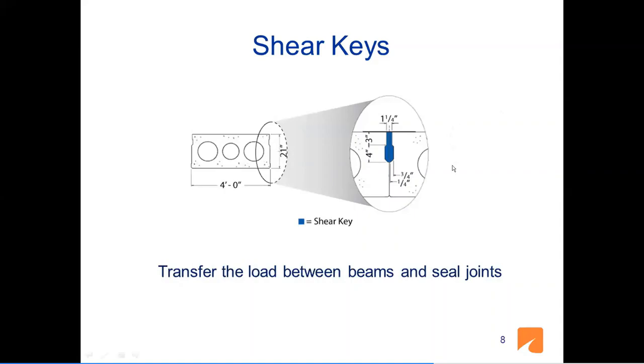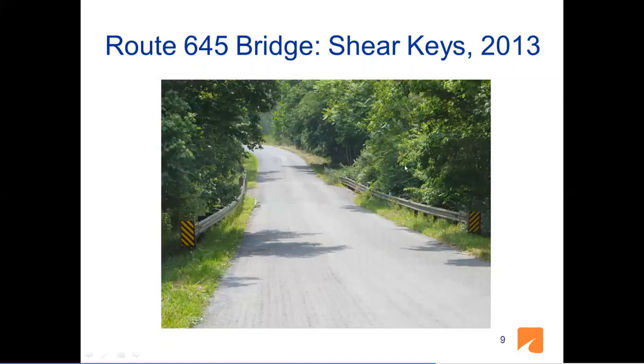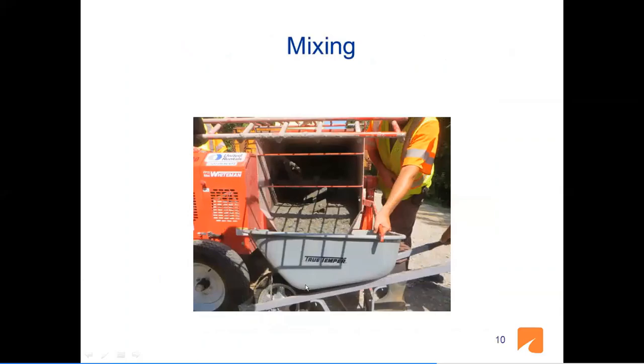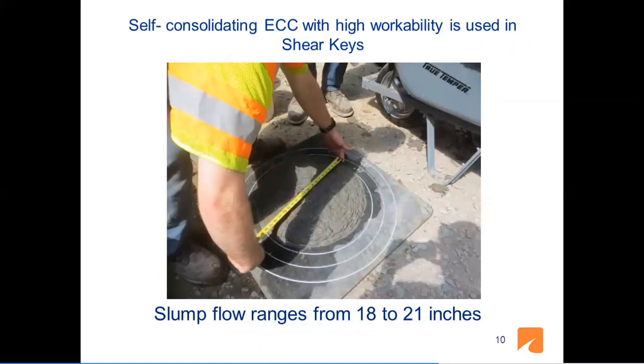So what we suggested is to use the fiber reinforced concrete, the ECC. So I'll tell you a little bit about that here. The shear keys basically transfer the load between beams and seal the joints. Our first application was in 2013 in this bridge. Since these are very small amounts in cubic feet, we used a mortar mixer. We batched up the material, went up to the site, and used this mortar mixer to place the ECC.